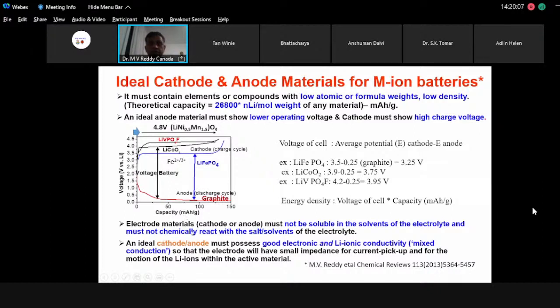Another important point is that both cathode and anode must not dissolve in the solvent in the electrolyte, nor chemically react with it. In all solid state batteries, the material must not react during sintering. We want a stable interface with both cathode and anode. Also, good lithium ionic and electronic mixed conduction is very important, so that people can get fast charging. These are the minimum four important points you have to remember.